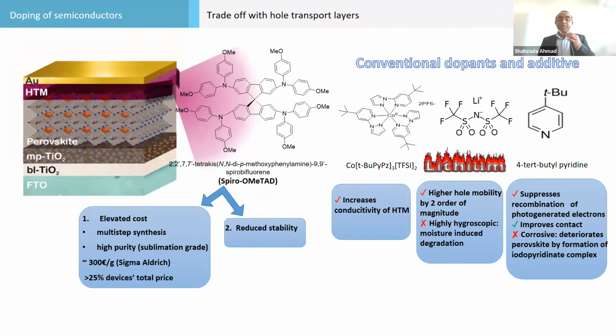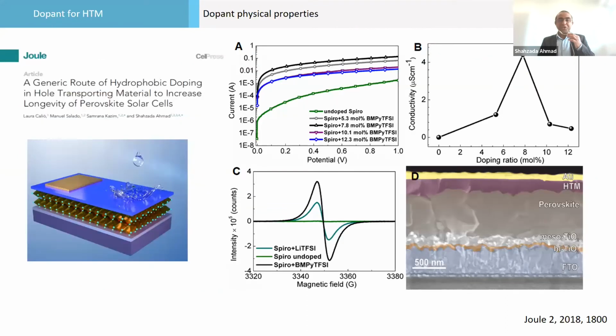But in the meantime, what happens if we develop a hydrophobic dopant? So for the last 20 years, we have been working on ionic liquids. So we took a TFSI ionic liquid, and we optimized the doping concentration. And we found that it worked effectively. We also monitored through EPR, and the charge carrier generation was higher than with spiro TFSI.